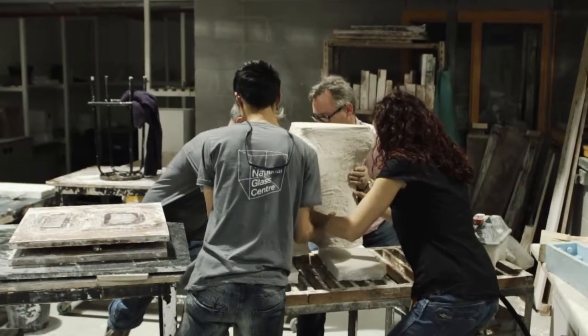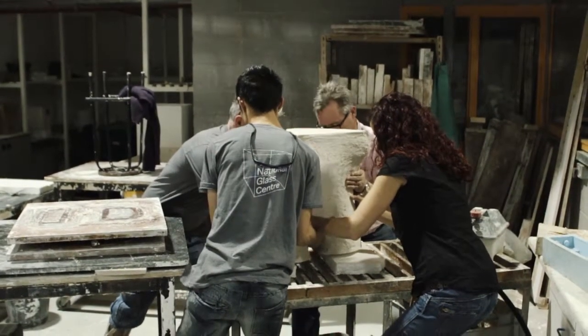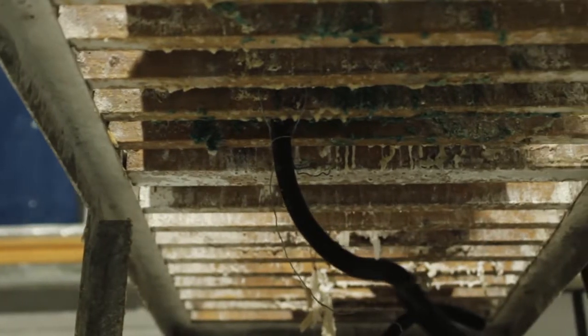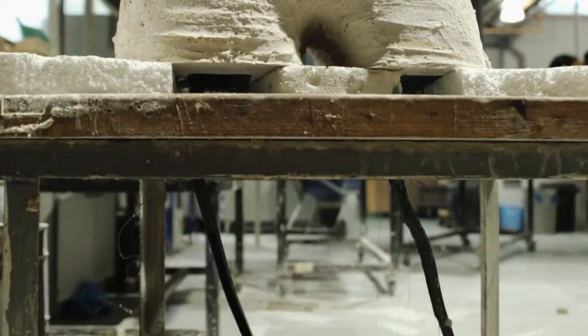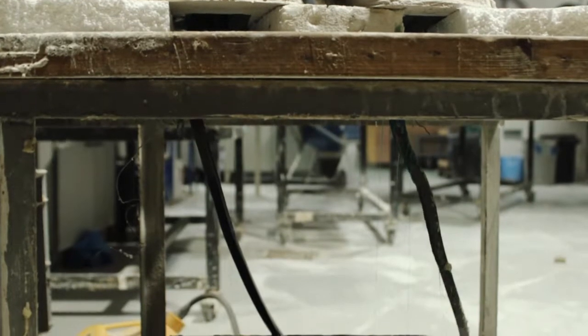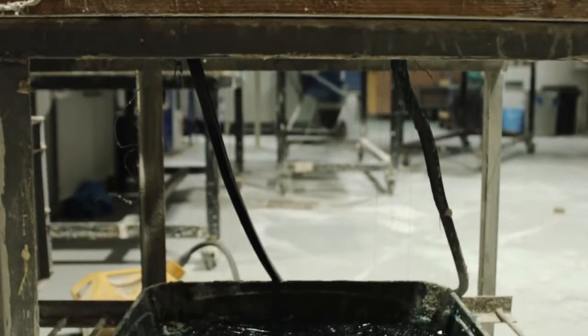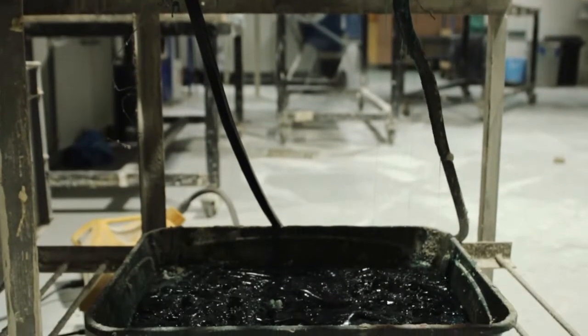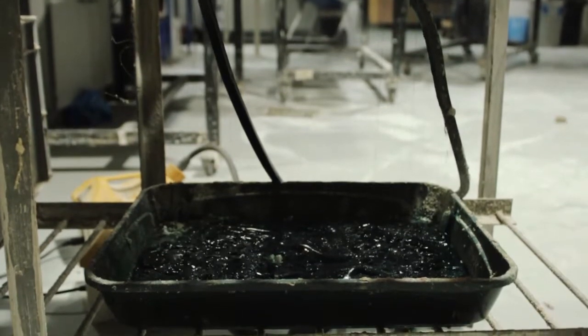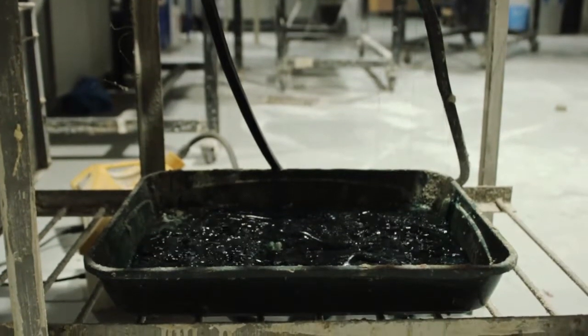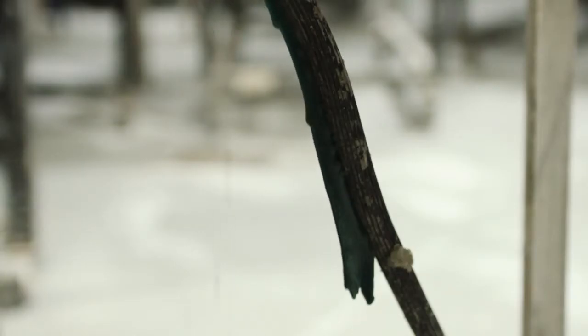Once this is done, we take the mold, we transfer it to a steaming area, and this is where we take essentially steamers and we steam out the wax. This process takes about 45 minutes. So I normally put 2 steamers, 2 hoses, and just wait until all the wax is drained out from the mold. Once this is done, we flip the mold upside down, and we let it dry.